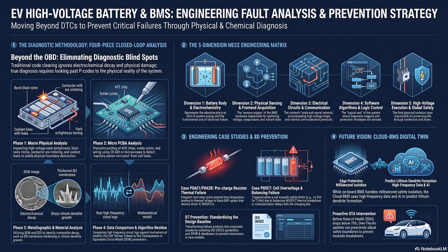But I want to dig into the why. What is the root cause? Why does a single cell become the short stave in the barrel in the first place? The expert analysis in the document points back to something we discussed earlier, the formation of dendrites, but it adds a very specific and highly controversial context here. Yes, the document details how specific charging habits can create a weak cell. It explicitly states that repeated, shallow charging cycles can trigger the growth of metal dendrites, which eventually pierce the separator and create a high-impedance micro-short circuit inside the cell. And this micro-short leads to what engineers call massive high self-discharge. Additionally, if this single cell is located in an area of the pack with poor local heat dissipation, its SEI layer will grow excessively thick, severely shrinking its true capacity.